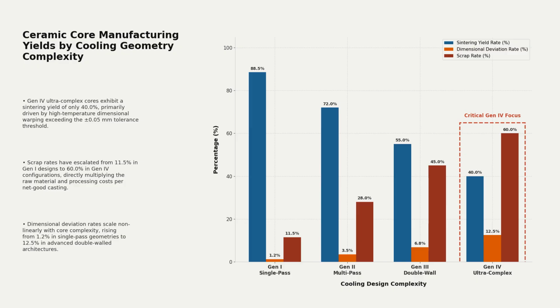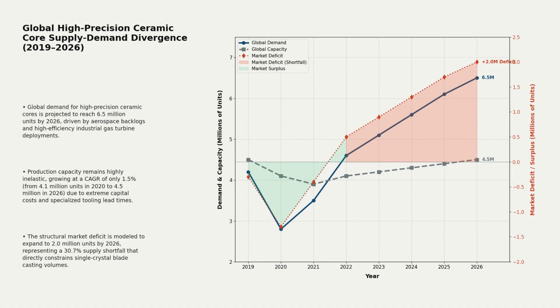This warping frequently exceeds the strict tolerance threshold of plus or minus 0.05 millimeters. Consequently, scrap rates have escalated to 60%, multiplying processing costs per net good casting. This physical limitation represents a critical barrier to increasing turbine thermodynamic efficiency. This yield collapse has created a severe macroeconomic supply-demand divergence.